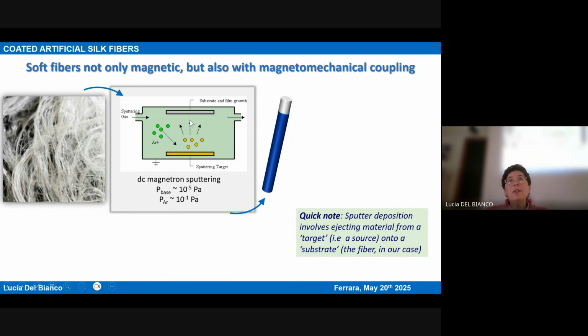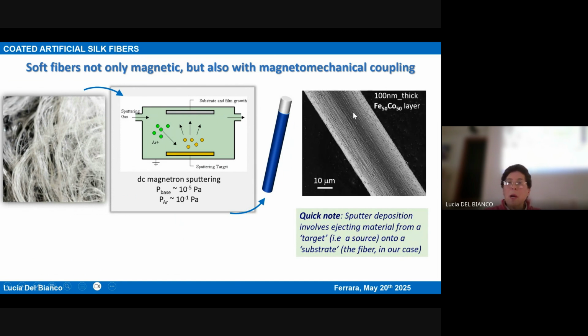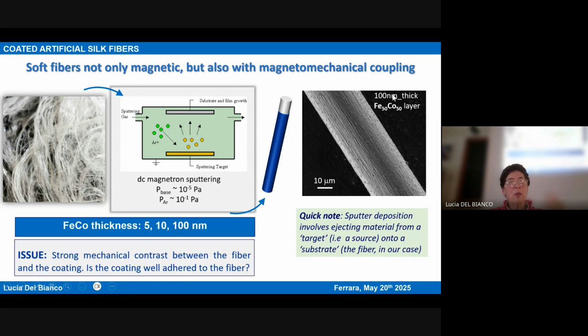And the fact is that normally the substrate is flat. For instance, a silicon wafer. In this case, it was our micrometric fiber. But apparently the things work well, and this is what we obtain in the case of a thickness of the iron cobalt of 100 nanometers, because actually we prepared 3 different types of fibers with a thickness of the iron cobalt of 5, 10, and 100 nanometers. But here again, is the coating really well coupled to the fiber? We didn't know in principle. The problem is always the strong mechanical contrast between the fiber and the coating. But we can have an answer to this question by performing a magnetic characterization.